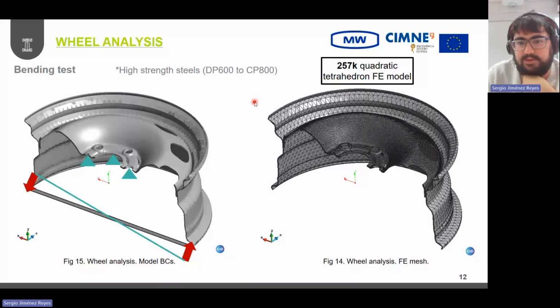perform the fatigue simulation. Here you have an overview of the finite element mesh that we use for conducting this simulation. And you can see here a comparison between the experimental result in terms of crack location and the one obtained numerically. So we can capture perfectly this type of crack pattern observed experimentally.